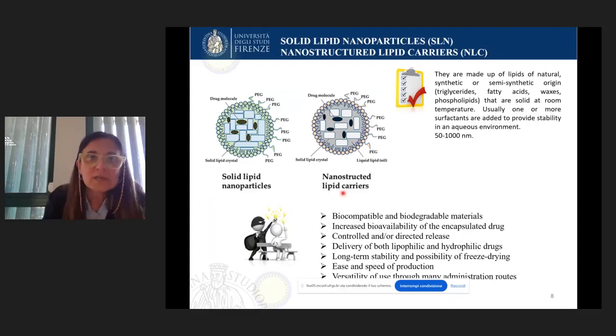About the lipid nanocarriers, we have solid lipid nanoparticles, SLN, and nanostructured lipid carriers, NLC. Solid lipid nanoparticles are solid at room temperature, and the core of the carrier is made of solid lipid. Around it there is a layer of tenside. In the case of NLC, inside the nanoparticles there are solid and liquid lipids. The presence of liquid lipid improves the load capacity and also the stability of the carrier, because in the case of SLN it's possible to have expulsion of the drug during storage.